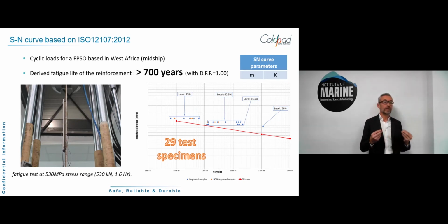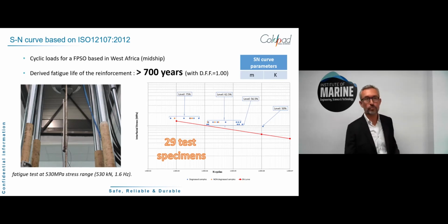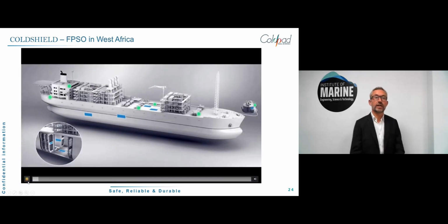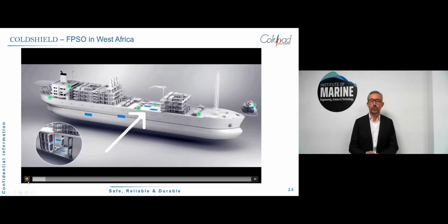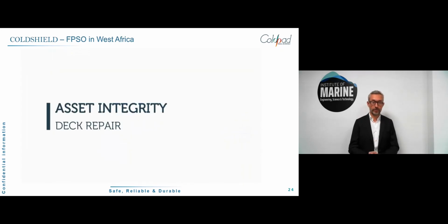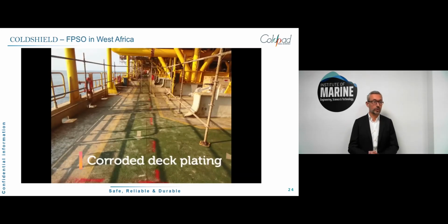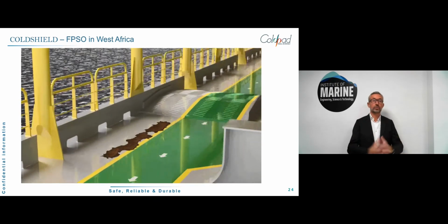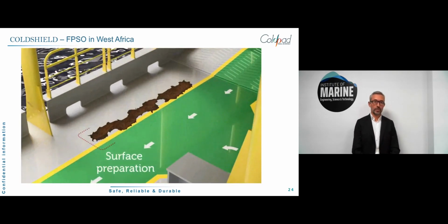So meaning that even if you take the worst case, which is a safety factor of 10, we still achieve 70 years of design life in fatigue. Right? So now, the project itself, in West Africa: a big FPSO producing more than 100,000 barrels per day, with a corrosion level which is quite high and which is basically requiring repair.